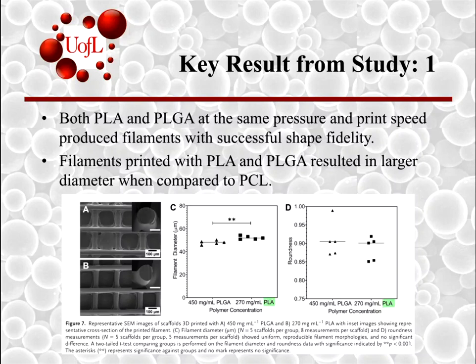It's important to note that the PLGA and PLA inks both produced filaments with roundness values of 0.85 or higher, which indicated successful shape fidelity, and these showed no statistical differences from one another. The results of this study confirm that the relationship between ink viscosity and print parameters can be applied to reduce optimization steps and parameterize space to achieve reproducible structures with solvent cast printing. The effects of PLA are shown in Figure 7, Parts C and D, and the images in A and B show a microscopical structure of what the scaffold looks like up close. And as you can see, there is little to no statistical differences between the PLGA and the PLA.